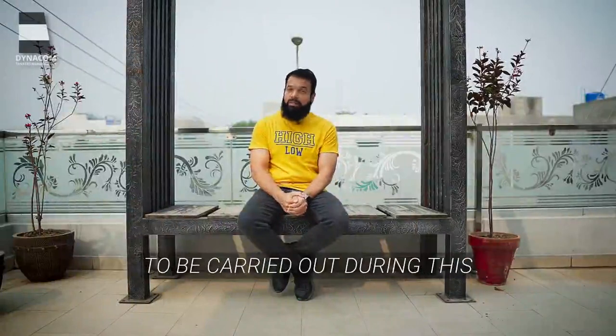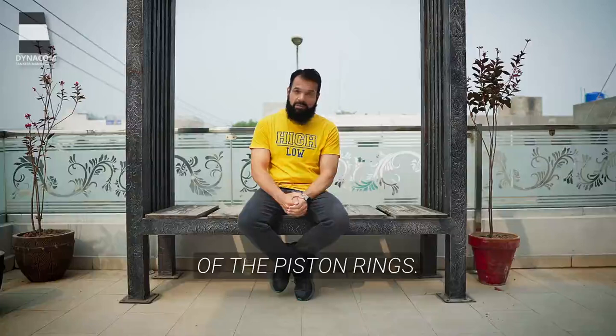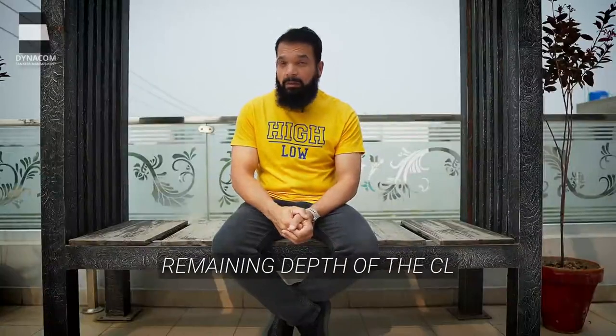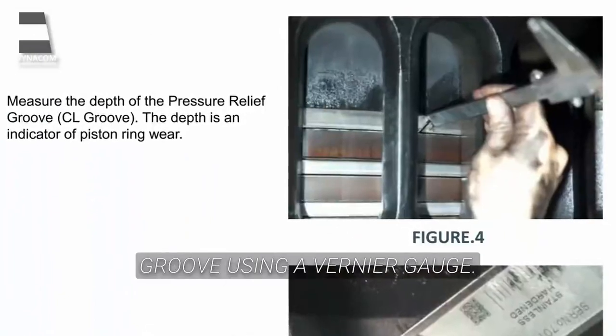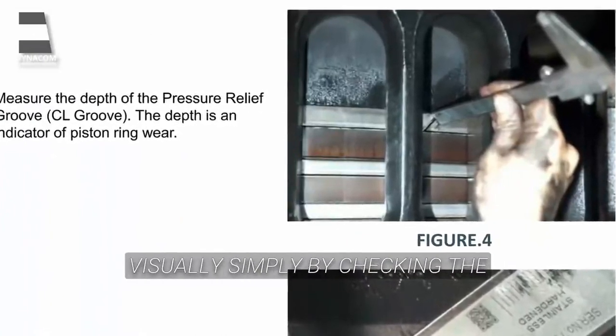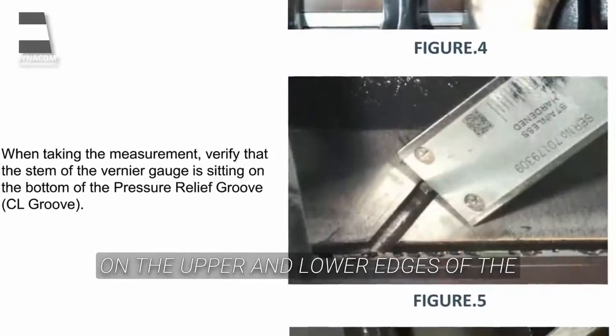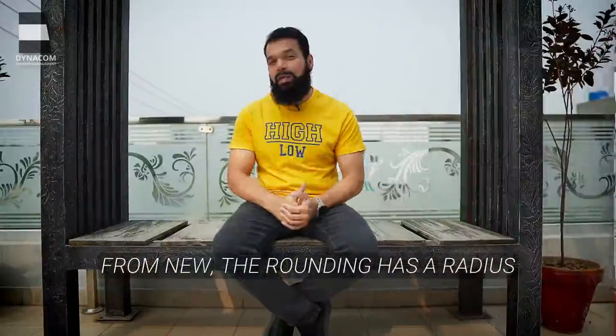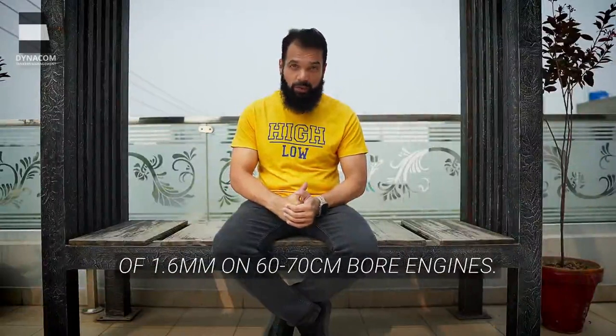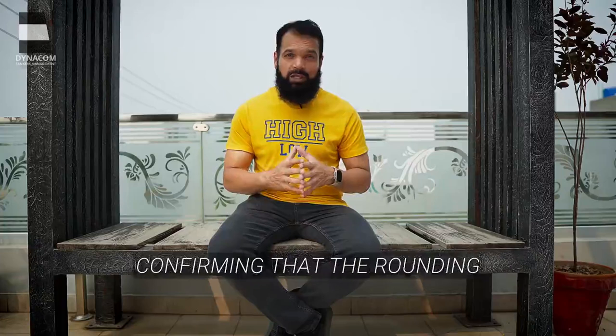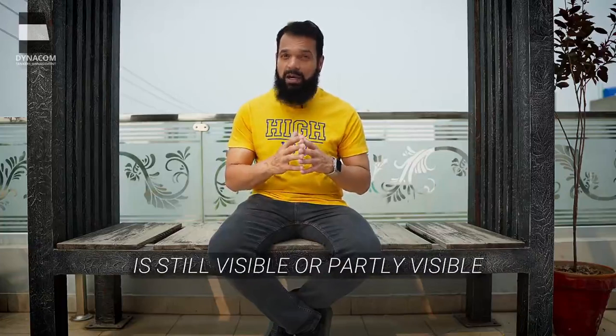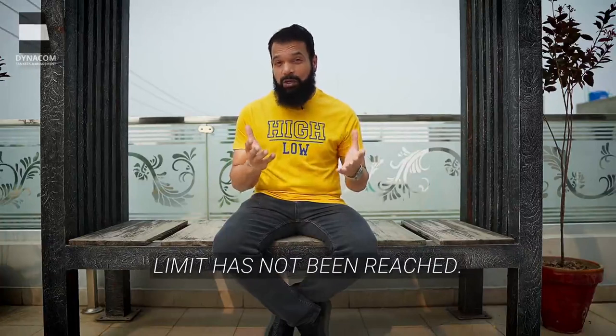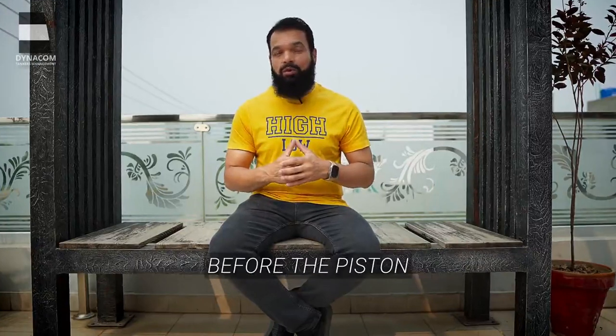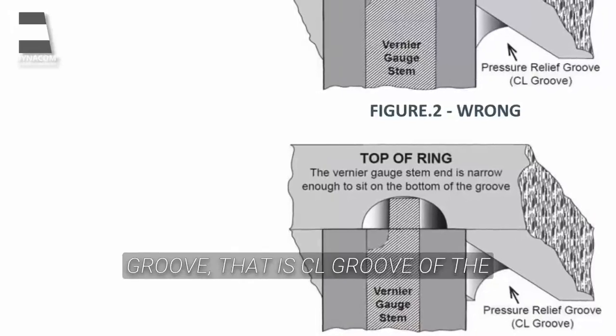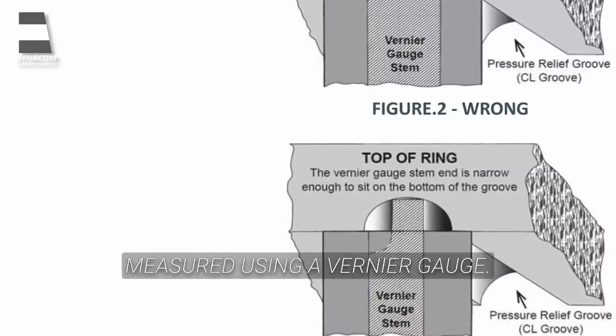the free vertical movement. Another important thing that needs to be carried out during this inspection is wear measurement of the piston rings. The wear on the top piston ring can be determined by measuring the remaining depth of the CL groove using a vernier gauge, but wear can also be estimated visually simply by checking the size of the remaining rounding on the upper and the lower edges of the running surfaces. From new, the rounding has a radius of 1.6 mm on 60-70 cm bore engines. Thus, a simple visual inspection through the scavenge ports confirming that the rounding is still visible or partly visible is an indication that the wear limit has not been reached, that many more hours are left before the piston overhaul is necessary. The depth of the pressure relief groove, that is the CL groove, of the top piston ring is to be measured using a vernier gauge.